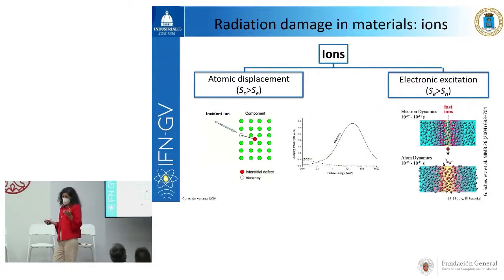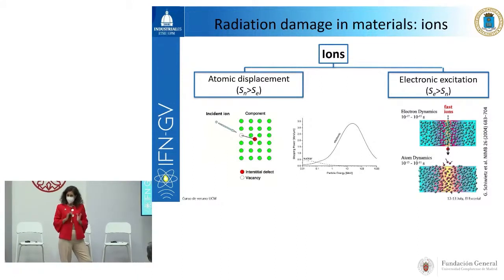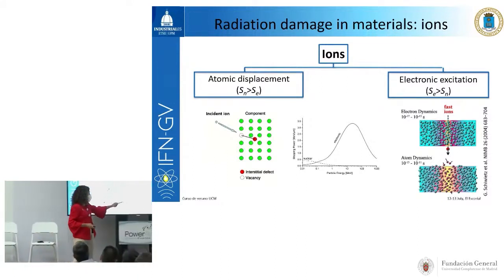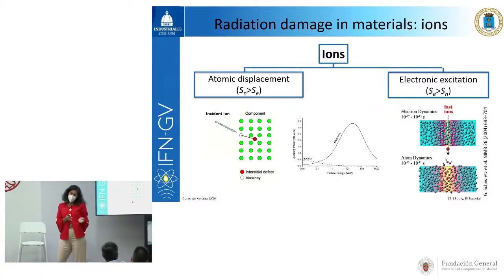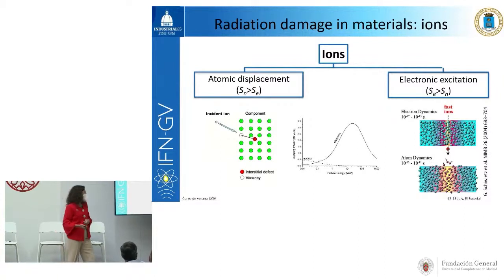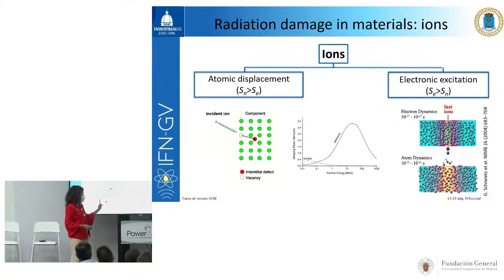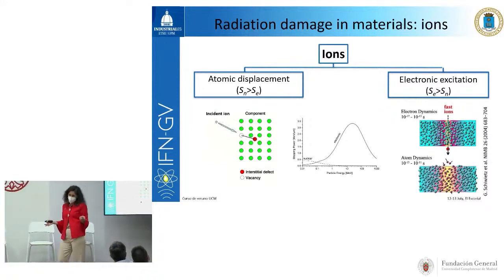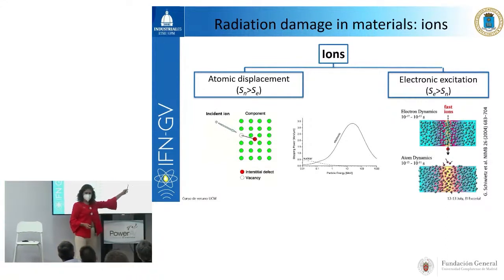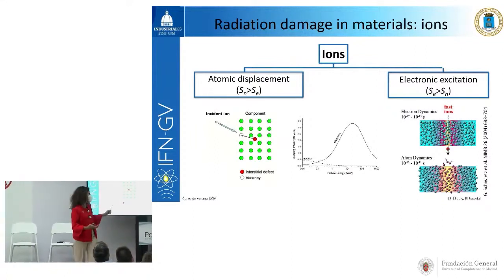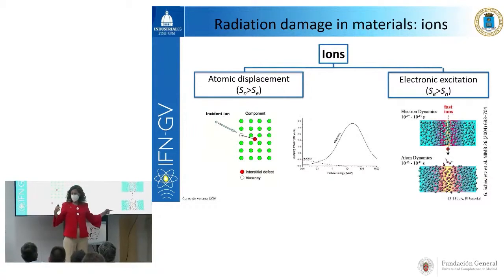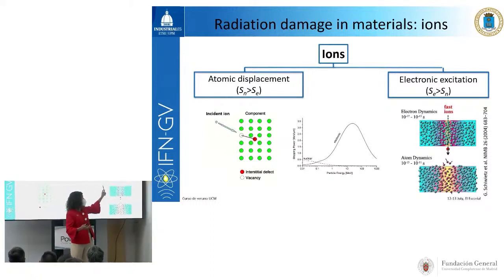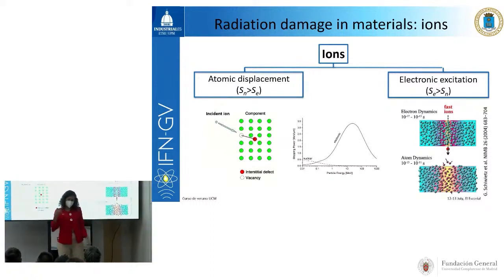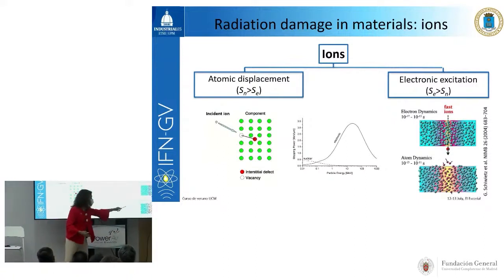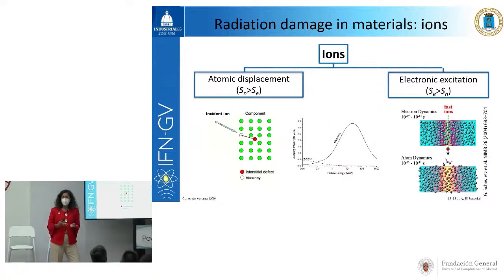In the case of ions, we have to remember that ions have two different energy regimes, okay? If we have low energy ions, the nuclear stopping power is going to be much larger than the electronic stopping power. So those ions are going to produce atomic displacements, as in the case of neutrons, okay? And when we have electronic excitation, where the electronic stopping power is much larger than the nuclear stopping power, then the mechanism is completely different from this one. So the ion energy is transmitted to the electron lattice, and then from the electron lattice, by different mechanisms, it is transferred to the atoms, okay? And finally, we can create ion tracks, okay?